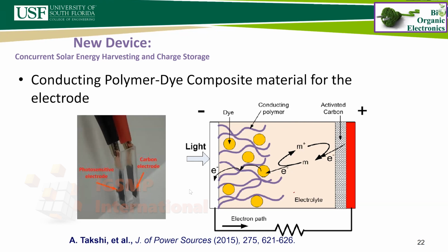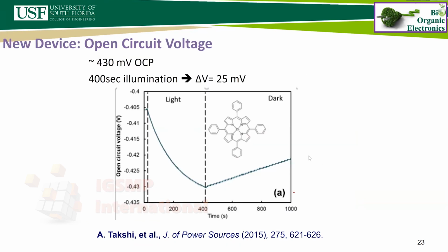So we took that concept and put it into practice by designing a very simple cell, taking one counter electrode, a carbon electrode, and a transparent electrode coated with a mixture of the conducting polymer and the dye. And surprisingly, we saw that it's actually working very well. This chart is showing the open circuit voltage of the cell, but of course it's negative because of the polarity of the working electrode versus counter. But if you notice, when the cell was exposed to the light, the magnitude of the voltage actually increased from about 400 millivolts to 430 millivolts.